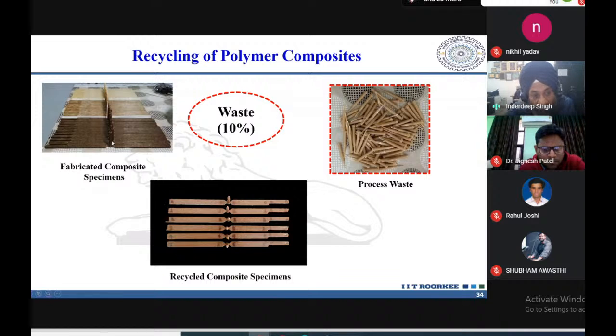Now if you see here, this is the sprue through which the material enters the mold cavity, and these are the waste. This material, we cut the sample from here. This is the flexural sample, this is the impact, and this is the tensile. So once we cut it, all you see here, all the sprue, this is the waste material. Normally, we have seen that it is 10% of the overall weight of a single sample. So this is one shot, and out of this, if we calculate the weight of this sprue, this is 10%.